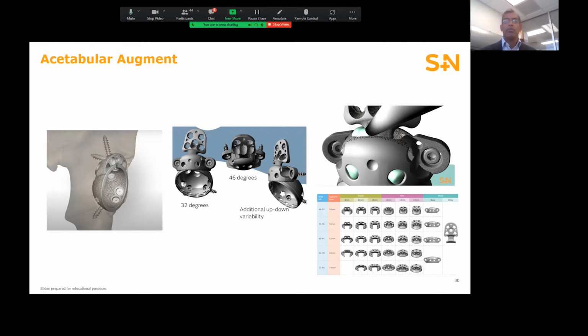The image at the bottom right corner displays multiple acetabular augments that we offer. And these augments can be attached in various configurations. Some of those are shown in this middle image. So there's some amount of freedom from a positioning perspective before the augments and shells are locked into place using screws. Once locked into place, bone cement is used to further fix the position of the augment relative to the shell. Due to the additively manufactured porous structure, bone can then grow into the surface to provide long-term stability of both the construct and defect.